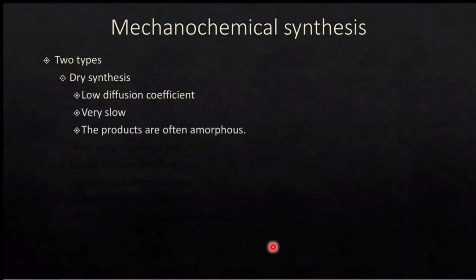But you're going to just grind your materials together, and that is going to diffuse them and allow your reactants to come together. The problem with using dry synthesis with no solvent at all is you have a very low diffusion coefficient. Basically, whatever your hand can do or whatever your machine can do, that is your diffusion coefficient. And so this can make the reactions very slow in some cases, and the products are also often amorphous because there's no solvent in order to support the pore formation, which can cause those pores to collapse.